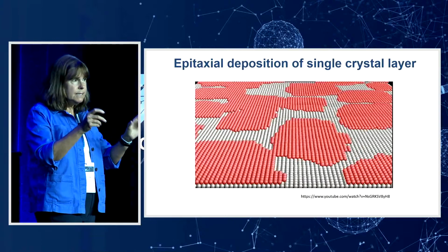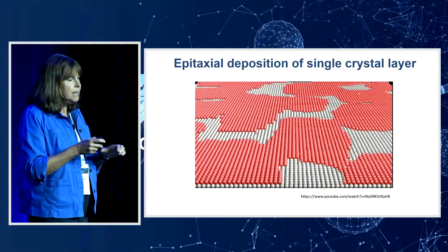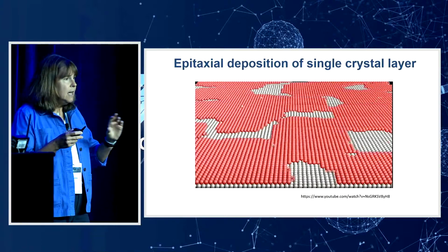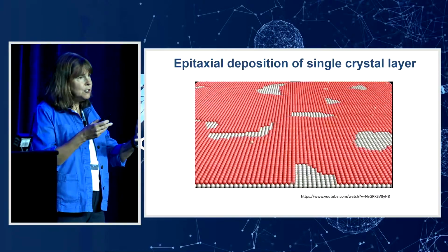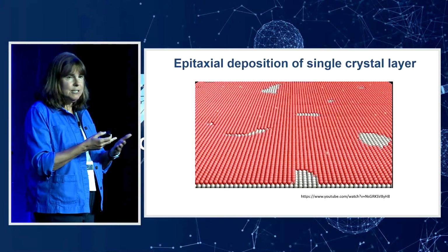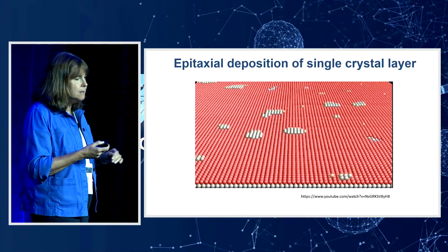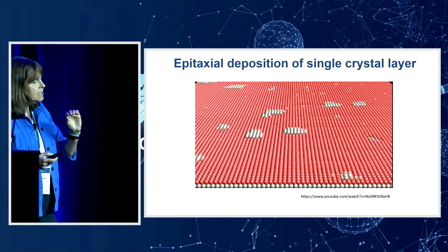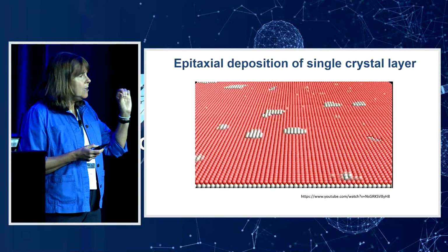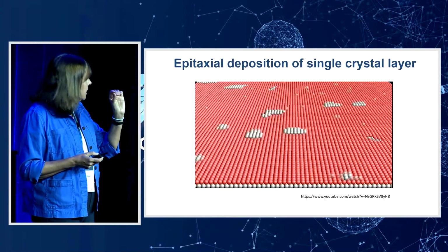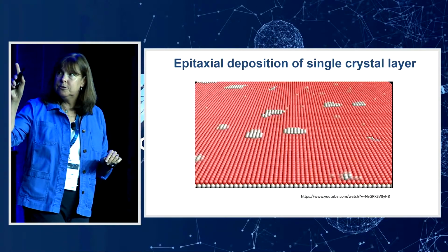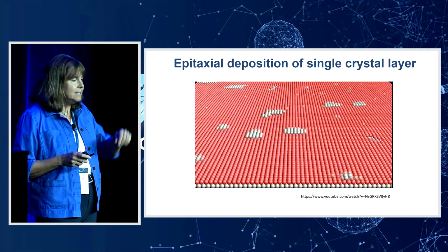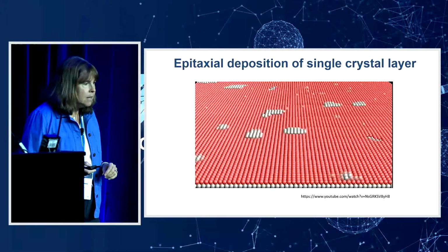So you start off with these islands that nucleate on the substrate. They grow in size. You can see from this animation that they're starting to come together to form a coalesced film. And then in addition to having the single layer, you may also get some bilayer islands that start to form. Those are the little additional white islands that have formed on top of the pink.